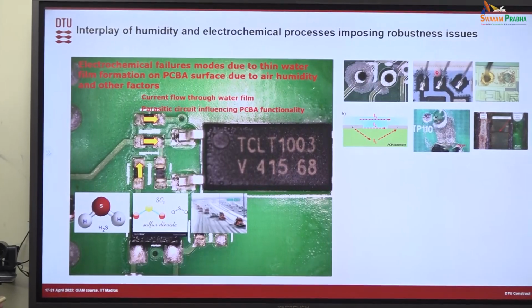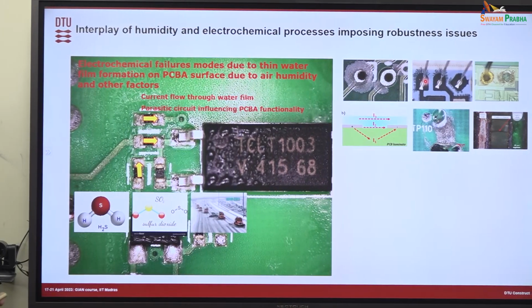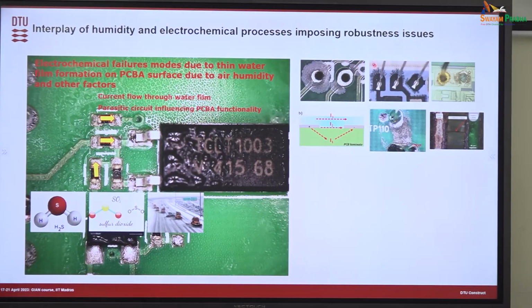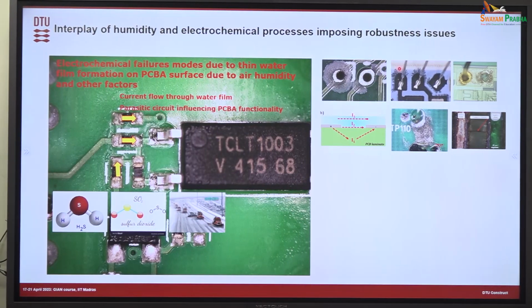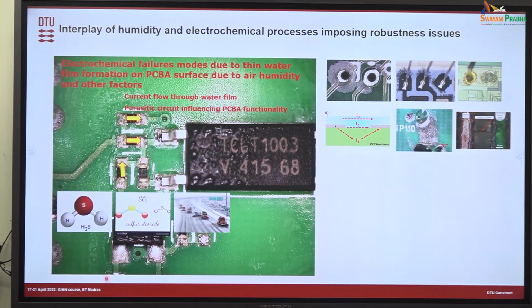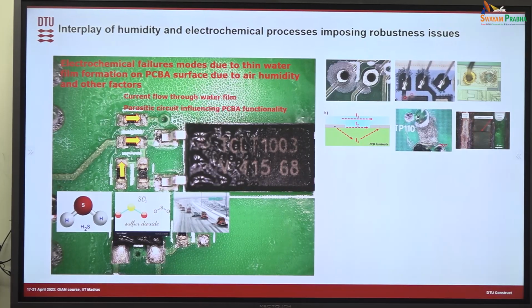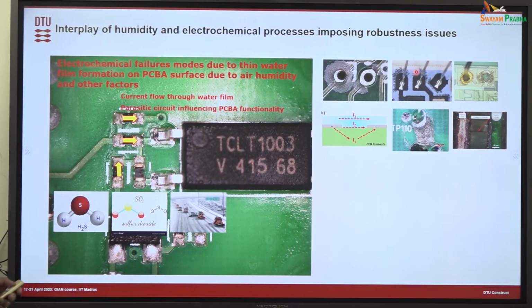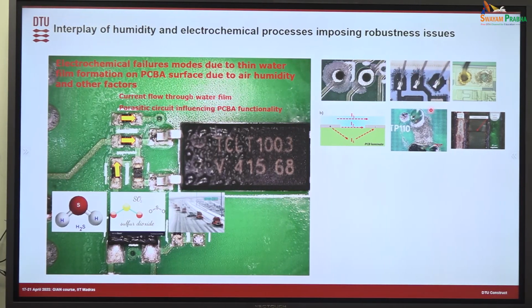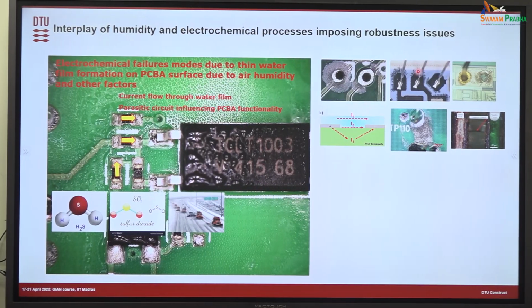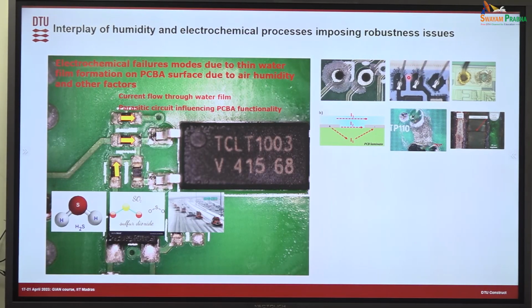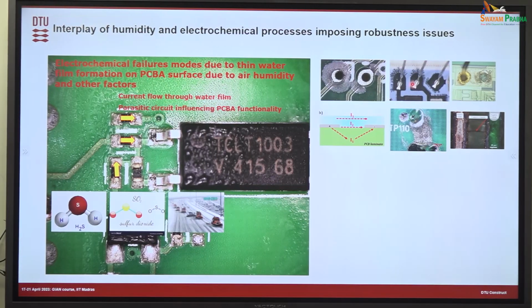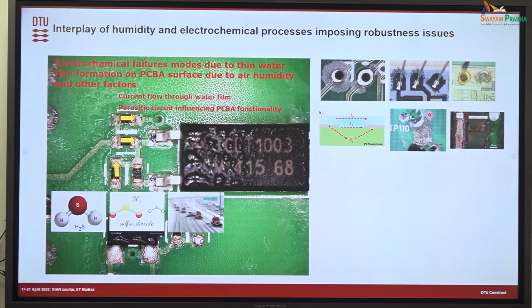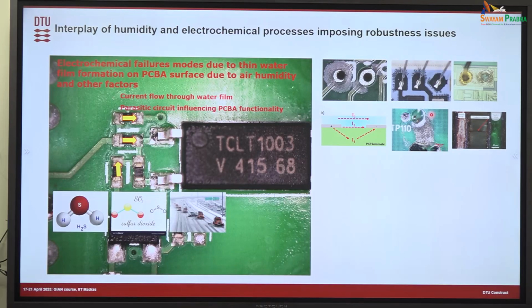This is another one, when you have silver on the surface. Silver dendrite is forming. This dendrite is silver sulfide. So it's in an H2S condition or SO2 condition. Silver will react and form this kind of dendrite formation. Again, dendrite formation itself is not a problem, but when the dendrite is forming, the thickness of the silver line is coming down because of corrosion. Silver is converted into silver sulfide.